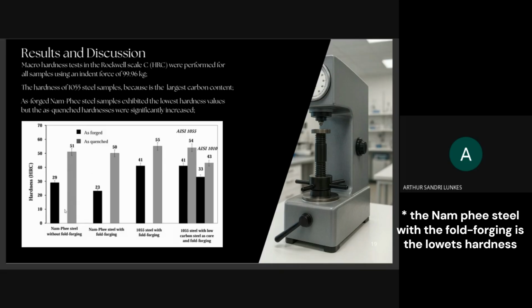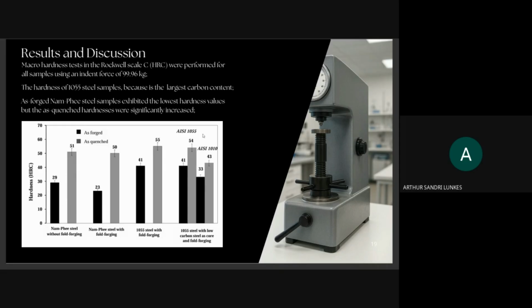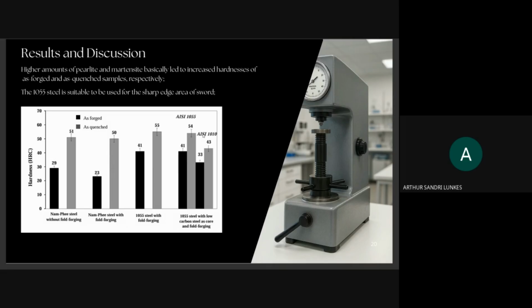And the NP steel with only forging has the lowest value for hardness. The high amount of pearlite and martensite basically leads to increased hardness of the forged and quenched samples respectively. And the 1055 steel is suited to be used for the sharp edge of a sword. It is utilized for this part of the sword because it has more hardness. Okay. I think that's it for this test.